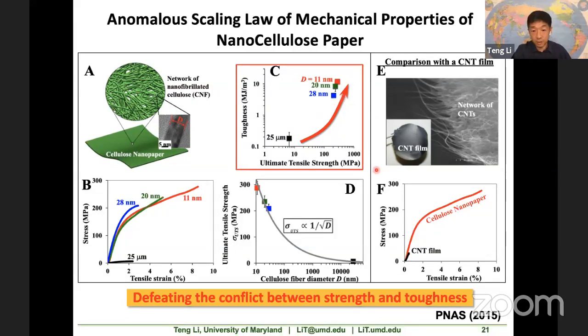The answer is no. We actually did a control experiment to show this. Now, this is a film made of carbon nanotubes. Carbon nanotubes, we know, are arguably one of the strongest materials in the world. The question is, if you are using the strongest fiber, carbon nanotubes, to make a piece of paper, are you making the strongest paper in the world? The answer is no. As you can see, we used carbon nanotube bundles with a diameter of about 10 nanometer, trying to compare with our best performing nanopaper.